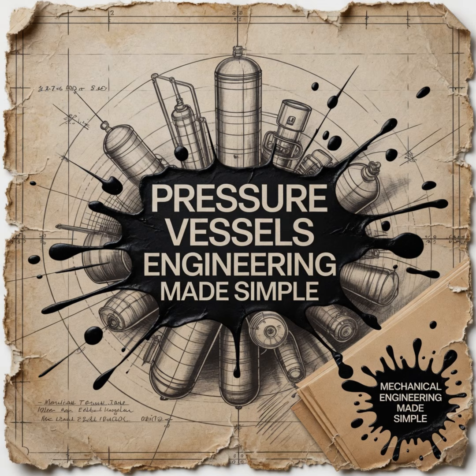They can, but there is a severe mathematical penalty. A penalty. Yeah, the code dictates that if you use a lower strength material for reinforcement, the area considered as effectively reinforcing the cutout must be decreased proportionately by the ratio of the allowable stress values of the two materials. Wait, say that again? Basically, you have to use significantly more of the weaker steel to achieve the same result. You have to make the pad much bigger or thicker. Oh, I see. Furthermore, when you weld two dissimilar metals together, the design calculations must assume the weld joint is only as strong as the weaker of the two parent materials. So you never get to claim credit for the high-strength steel if its weakest link is the material it's attached to. Never. The math won't let you. It's an incredibly strict system. But it makes sense.